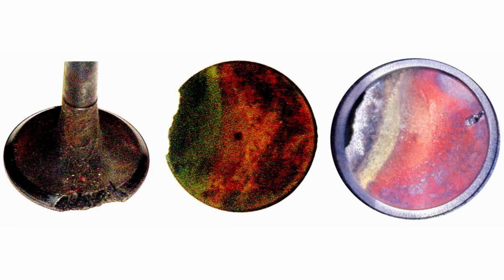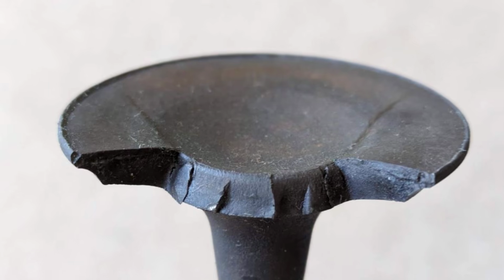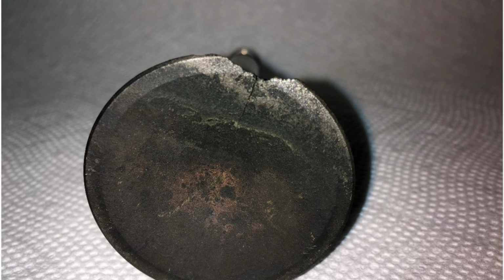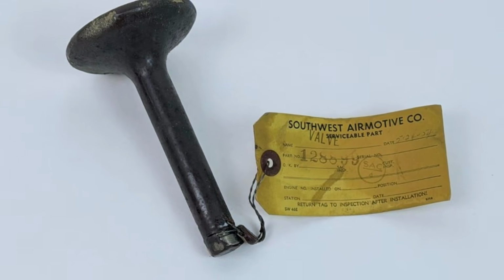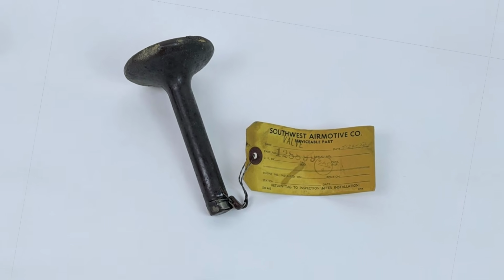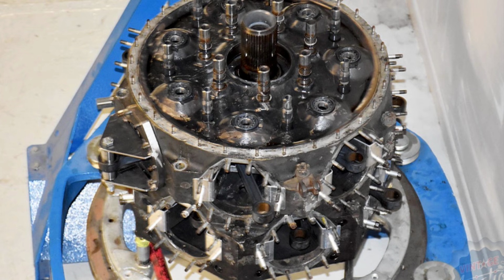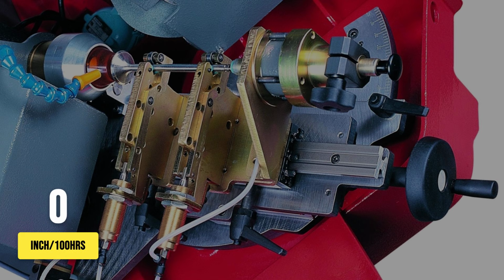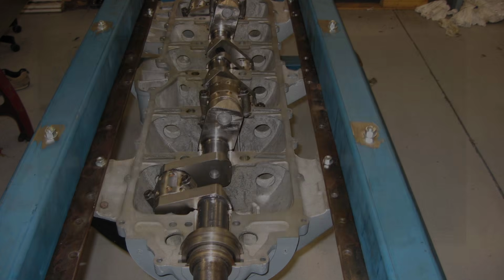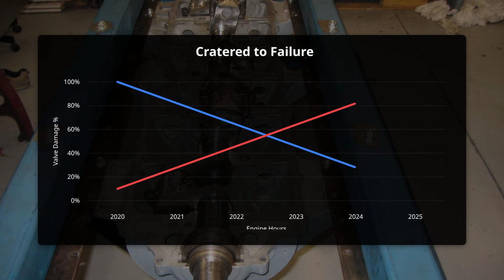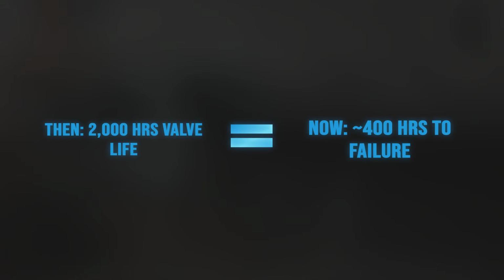On the bench, a mechanic holds up a shattered valve face, the edge missing in chunks. The invoice next to it lists not just a top overhaul, but a new seat, a new guide, and sometimes a new cylinder. The numbers do not lie. Unleaded operation can drive recession rates from 1/1000th of an inch per 100 hours, what you would see with TEL, to 10 times that figure. At that pace, a valve that once survived 2,000 hours is lucky to see 400 before catastrophic outcome.